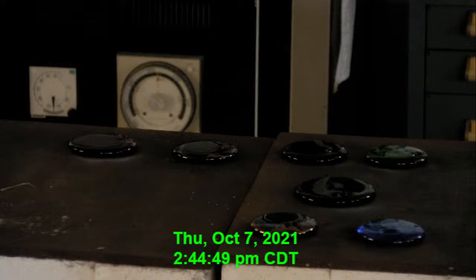So they're going to put it into an annealing oven. If this is melting at 1150, what ours is, we'd have to go down to like 600 Celsius. I think they call it 800 Fahrenheit is what they've got theirs set to. That's below the melting point, but above a softening point, so that bonds that are trapped in a stretched position can break and reform with atoms that are closer to them. That relieves the internal stress. So they're going to now run and put this thing they just broke off the pipe into an annealing oven.